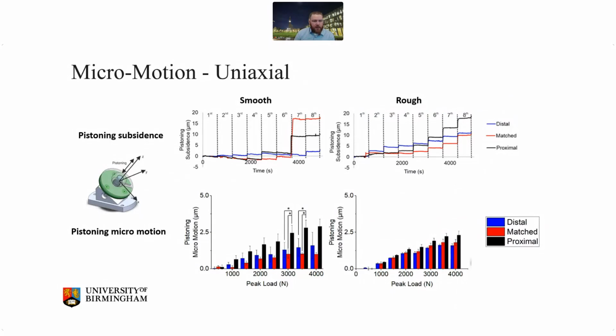Under uniaxial versus the ISO profile, so complex gait biomechanics, we found very different types and different levels of micromotion at the taper, and that resulted in different levels of measured corrosion as well. So for uniaxial, it was largely a pistoning motion and subsidence, where for the smooth taper, it basically sat relatively still until you reached a certain load, and then it slipped and migrated down the taper. Whereas for the rough tapers, there was this progressive subsidence going down.